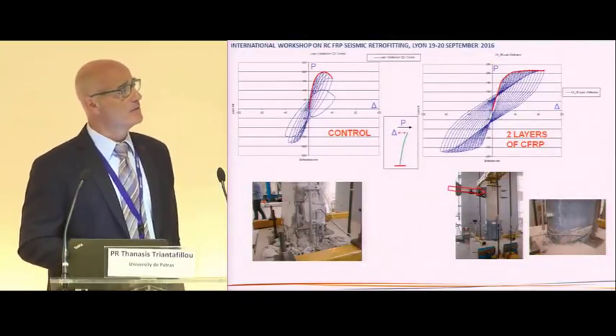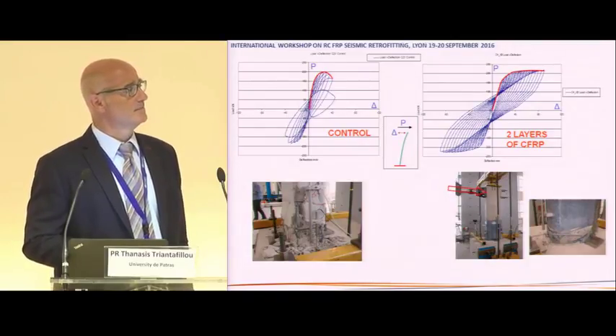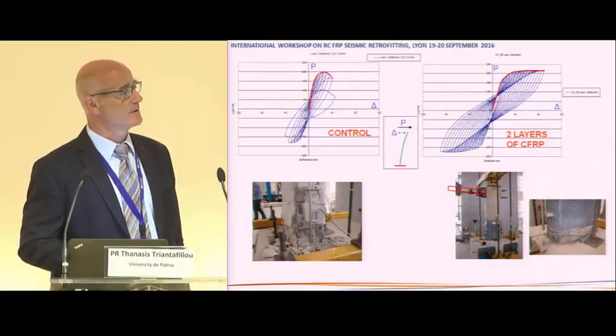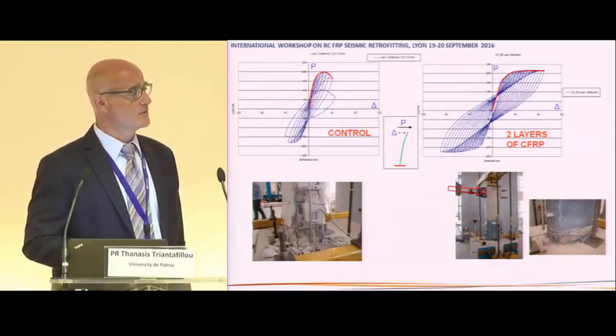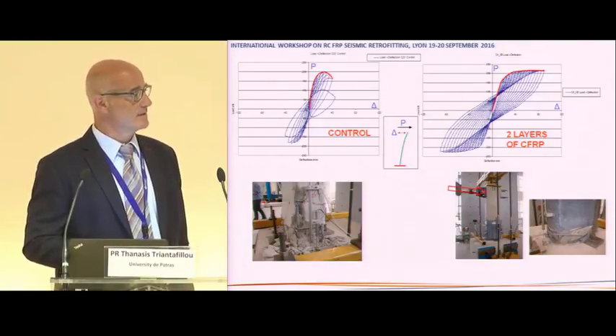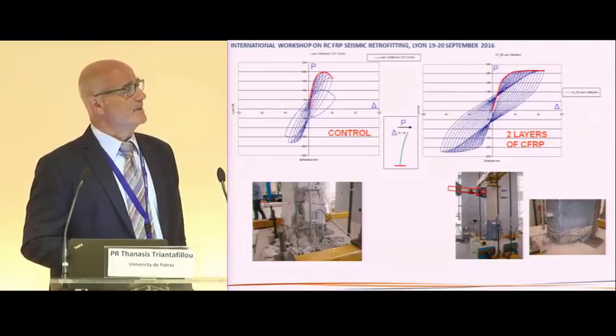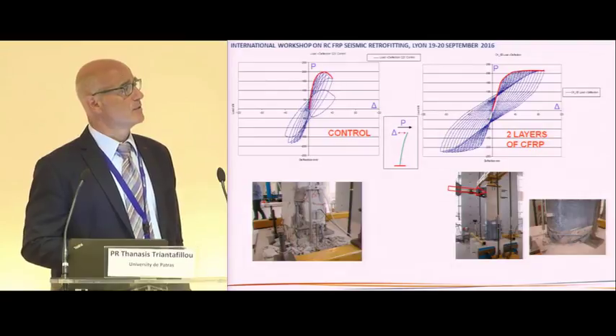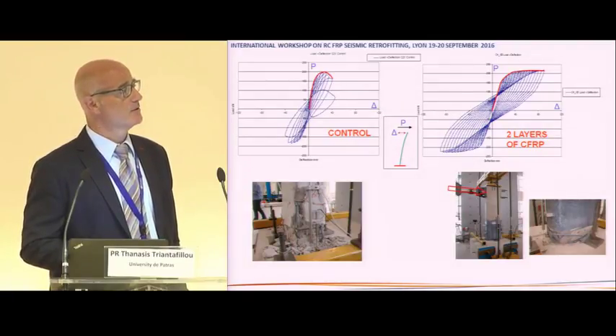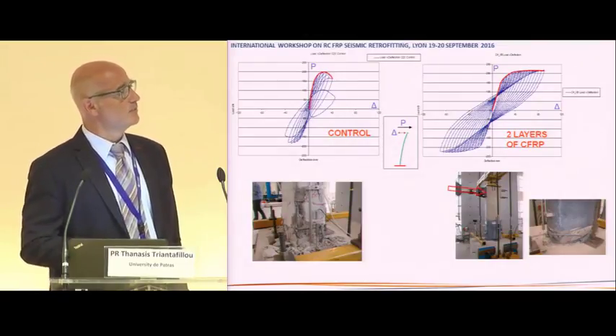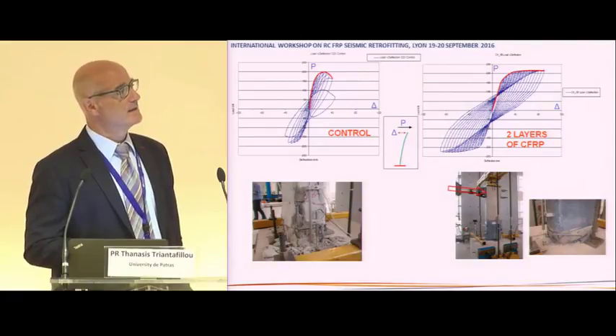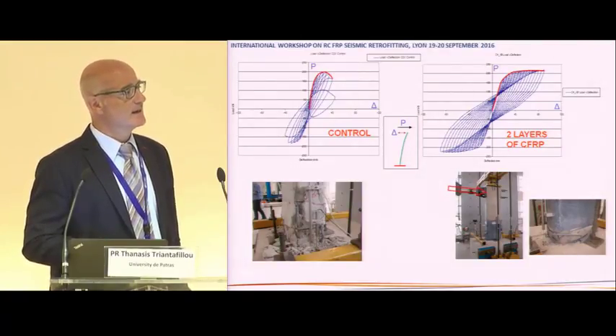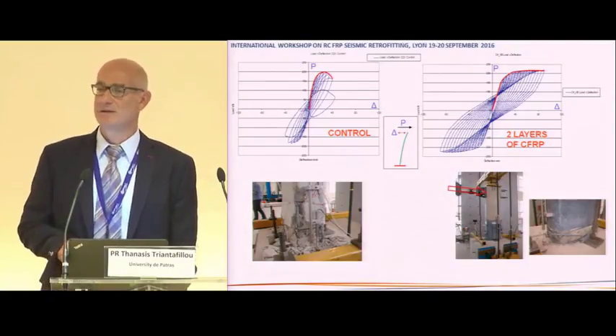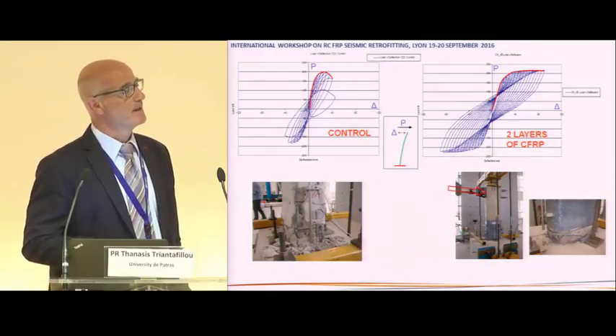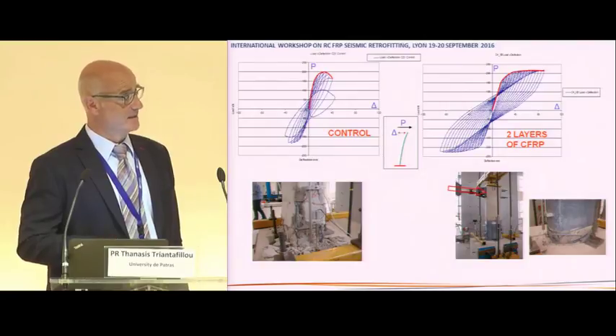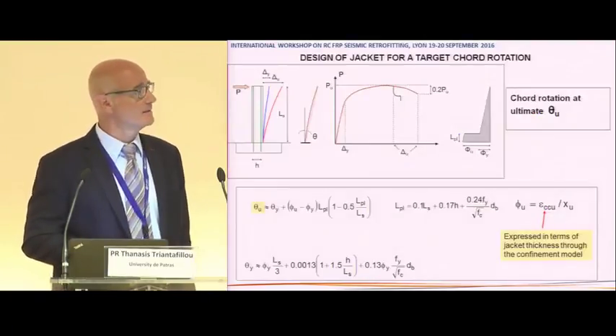And here is an example of how that increases easily by applying, for example, CFRP, a couple of layers of CFRP, even in columns with rectangular cross-sections in the order of 25 to 50 centimeters, as is the case in this photo. This is the response, the force versus the lateral displacement of typical columns. It is really important to emphasize that there is practically no increase in the strength. So we don't do this jacketing, this local confinement, to increase the strength of columns. We only do that to increase the ductility, to have a number of stable hysteresis loops and get a lot of deformation capacity. So strengthening is not the case.